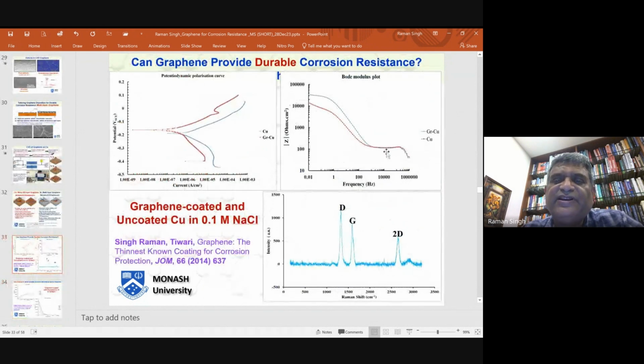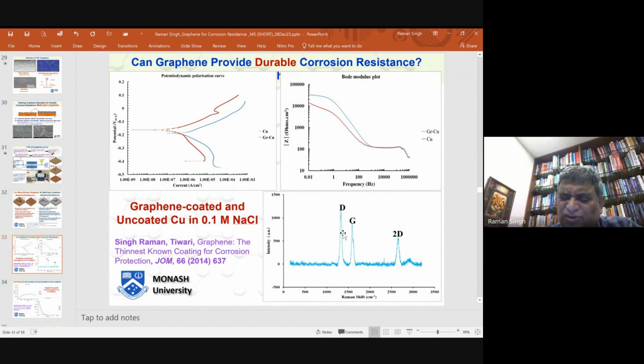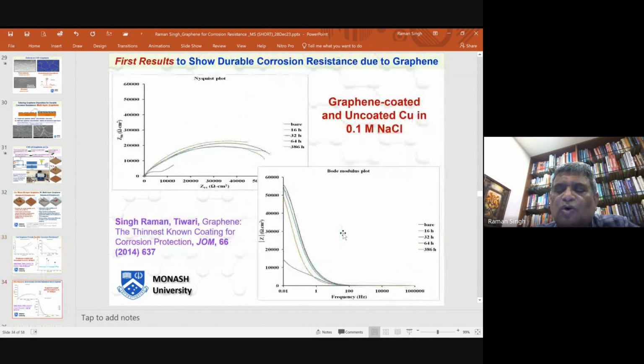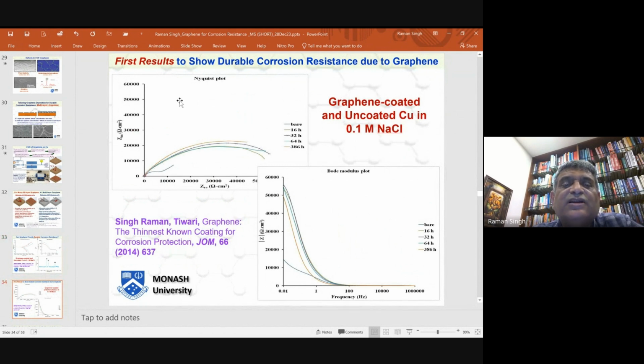So using that setup, we developed our own graphene. That graphene was multi-layer. As you can see, G peak is taller compared to 2D peak, but the graphene had lots of defects because of the tall D peak. So we could get improvement of only 10 times or so using our own graphene, but that was not the main purpose. Main purpose was to show that this graphene gives durable corrosion resistance. This student could do tests up to 400 hours, and whatever corrosion resistance was observed after a couple of hours, that sustained for 400 hours, that entire test duration.